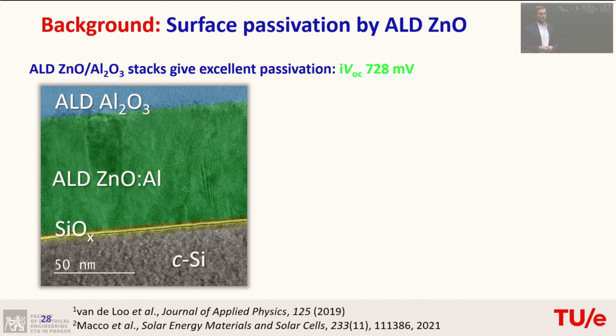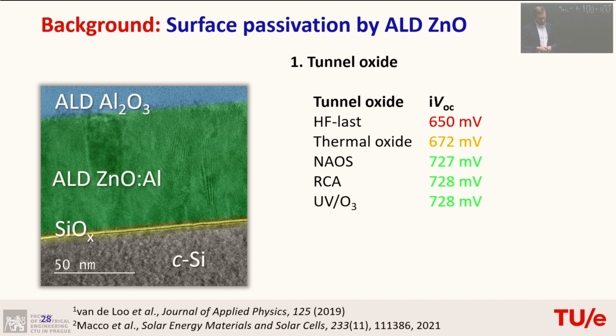So now the passivation quality is expressed in terms of the implied VOC. We see here that for different tunnel oxides, there are different values. So if you just HF dip your wafer and then you grow your zinc oxide, you don't get really a high value. But if you take care that you control this interfacial oxide well, so you can use, for instance, nitric acid oxidation of your surface or a typical RCA clean or UV ozone cleaning, and then you grow your zinc oxide on top of this, you all get quite nice values. So that's the first ingredient. We need to make sure that the interface is well controlled before you grow your zinc oxide on silicon.